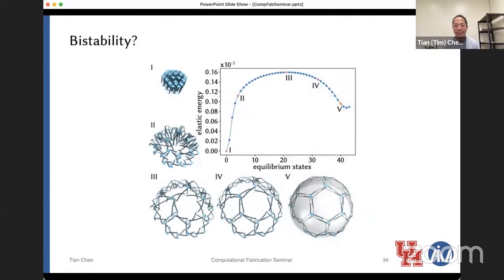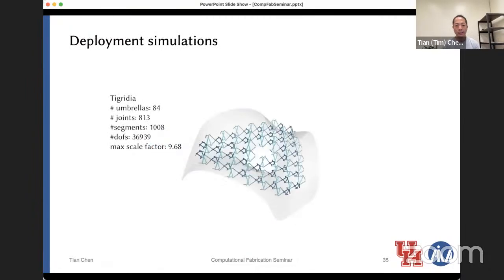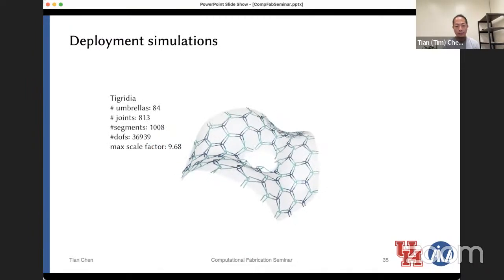One remaining thing we noticed almost by chance is that when deployed, the structure is stable. From the get-go, this wasn't what we were aiming for, but it does exhibit a local minimum in the elastic energy landscape, just like what we did before with the biaxial structures. So when we deploy the sphere, for example, the structure goes into a stable 3D state. We don't exactly know why yet, so this is something that we're still looking into. For positively curved structures, we have an intuition, but this also happens for negatively curved structures. And here are some deployment simulations of complex structures like C.